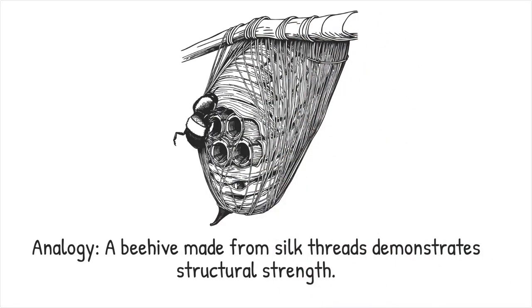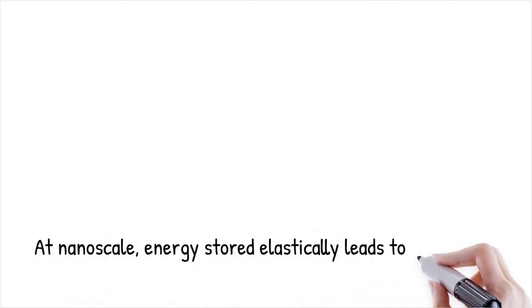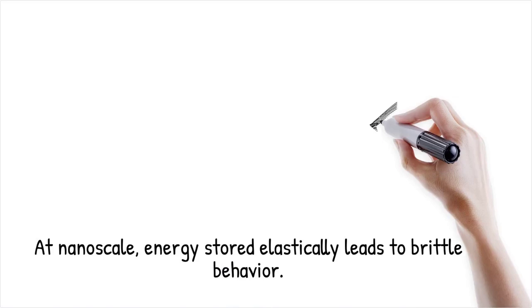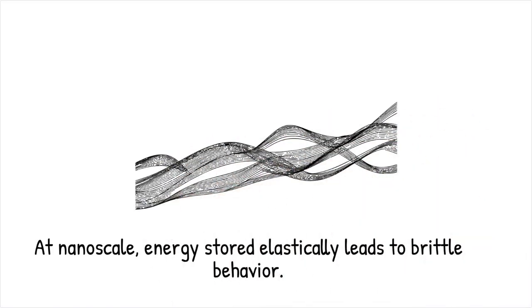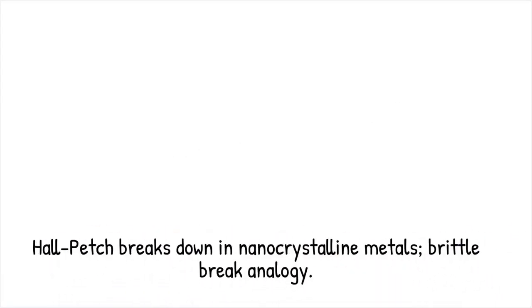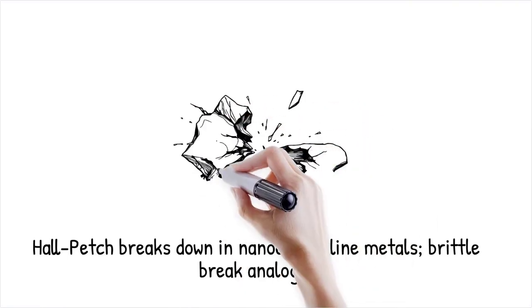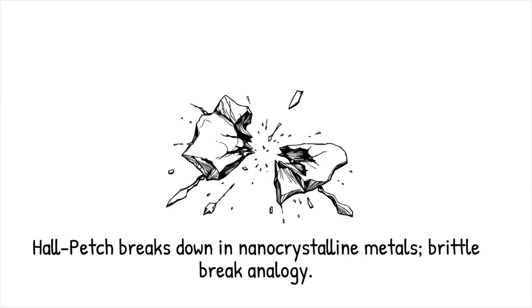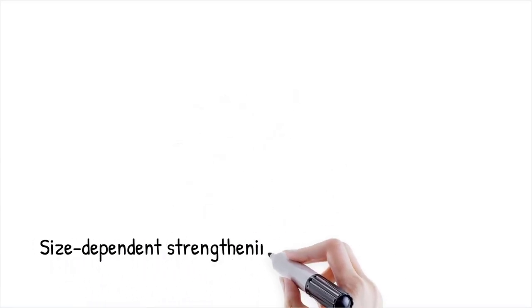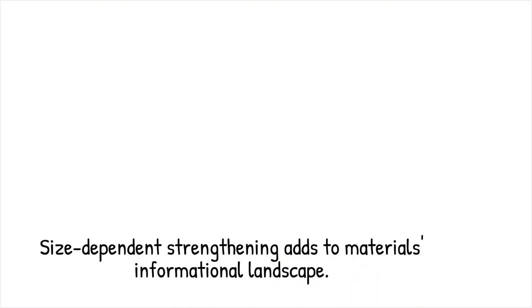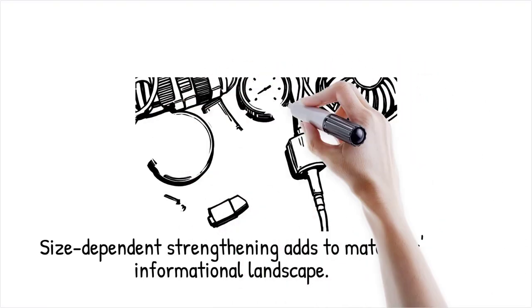At the nanoscale, the energy landscape for deformation and failure is dramatically altered, with fewer dislocations and limited defect accumulation, resulting in higher energy barriers to plastic flow. Energy that would otherwise be absorbed by defect motion is instead stored elastically, or released catastrophically upon fracture. In nanocrystalline metals, for example, the traditional Hall-Petch relationship breaks down at very small grain sizes because grain boundary sliding becomes dominant, changing energy dissipation pathways in a manner akin to snapping a cold spaghetti stick that stores energy until a sudden, clean break occurs.